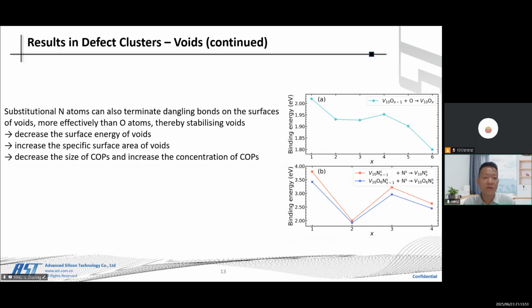Substitutional nitrogen atoms can also terminate dangling bonds on the surface of the void more effectively than oxygen atoms, thereby stabilizing voids. By decreasing the surface energy of voids, they increase the specific surface area of voids, decrease the size of COPs, and increase the concentration of COPs.